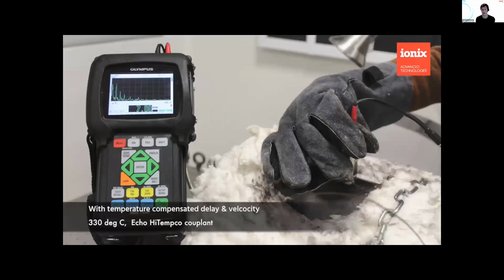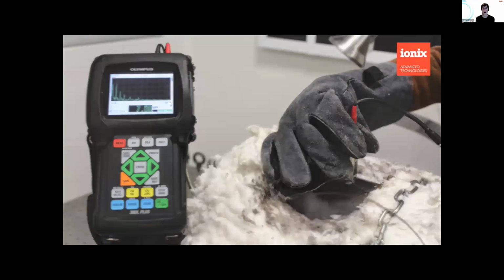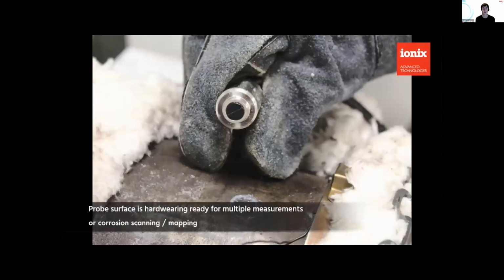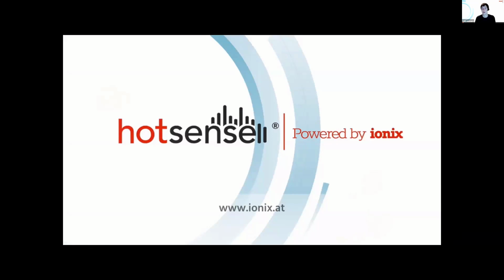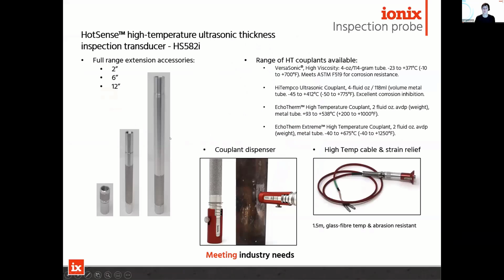We also supply a range of couplants for use with these probes. They're supplied by our partner Echo Ultrasonics, and those couplants are suitable for a range of temperatures, all the way up to 675 degrees C, so exceeding the operation of the probe. You would choose the different couplants based on the temperature you're operating in. We always recommend that you choose the lowest temperature rating for where you're working. It tends to be that the properties of the couplant perform better as you reach that optimum operating temperature range.